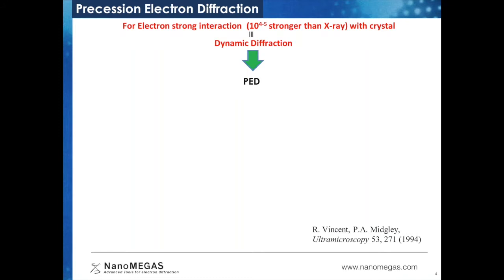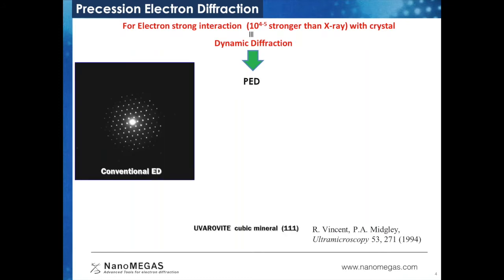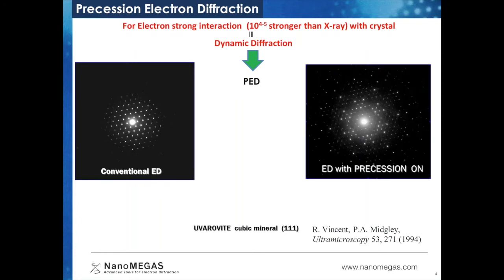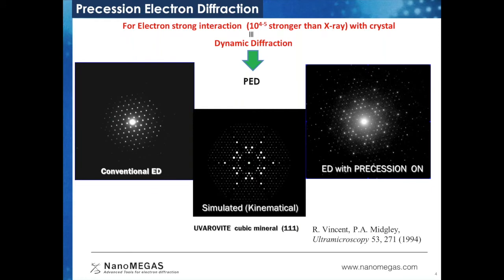precession in electron diffraction. For a cubic mineral, first a conventional ED dataset was collected. Then a second ED dataset was collected with the precession technique in the same orientation. And two obvious things you can see. First, there are more spots at high angles where the data was collected with precession. And second, there are intensity variations in the diffraction patterns. Now, if we compare the precession electron diffraction data and conventional ED data with the kinematically simulated data, we can see that the ED data collected with precession matches much more closely with the simulated kinematical data.